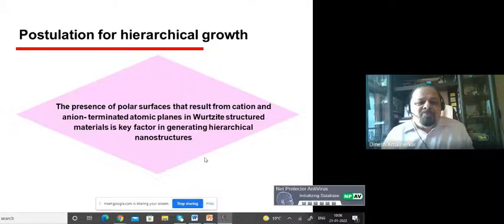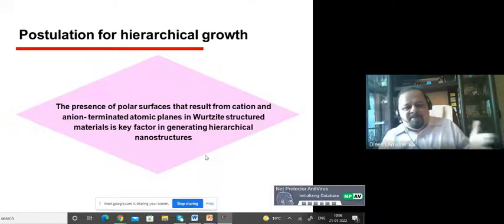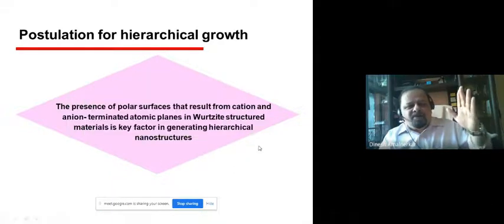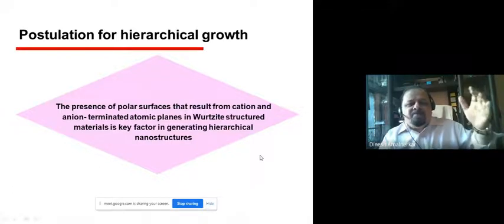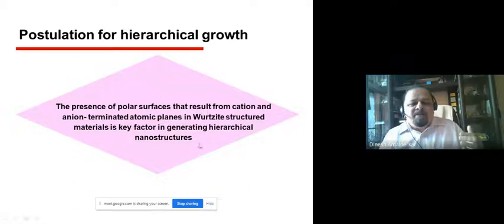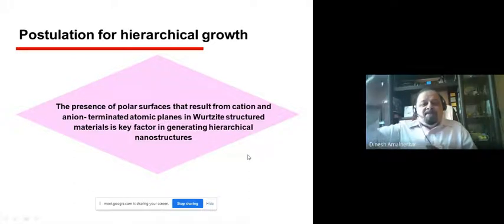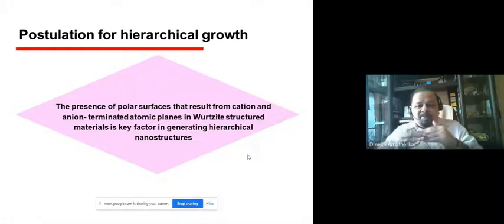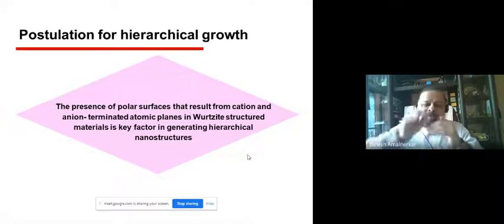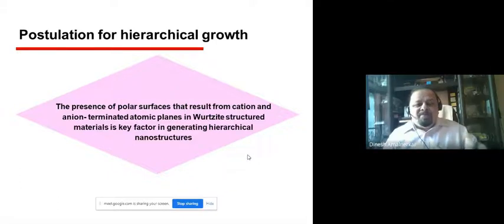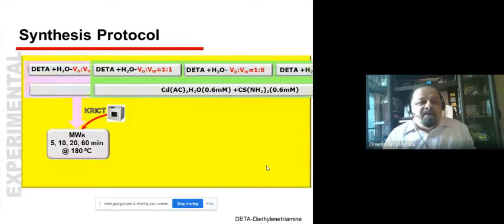Okay, the presence of polar surfaces, as I explained, it is a 002 preferred orientation, which either contains S or contains Cd ions. These are called cation and anion terminated atomic planes, which lead to hierarchical buildup in a typical hexagonal structure. Let me repeat again: the cadmium-containing plane comes in contact with the sulfur-containing plane, and there is a hierarchical one-dimensional buildup. This is the way we can explain the generation of hierarchical nano-architecture.